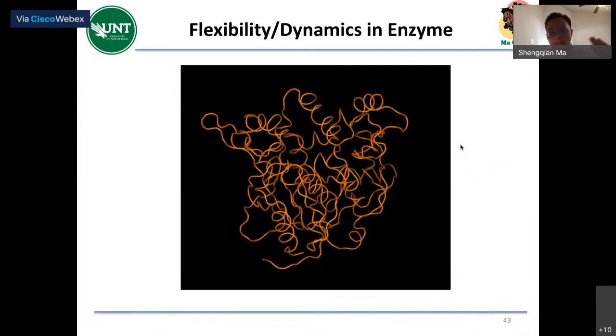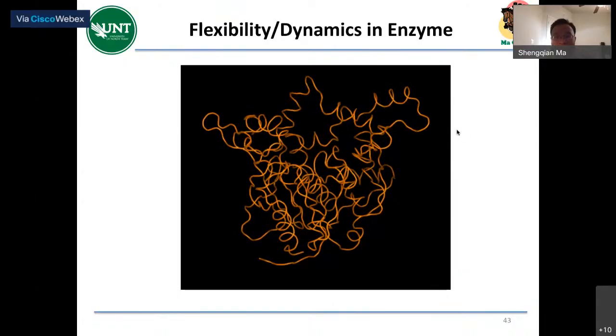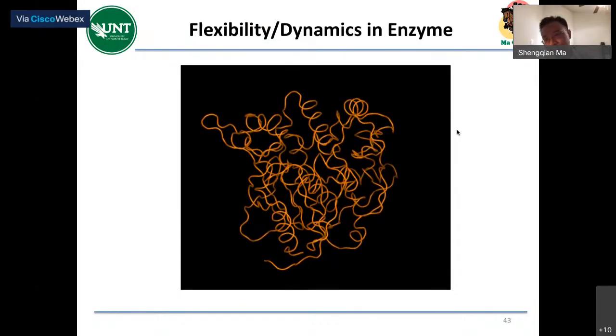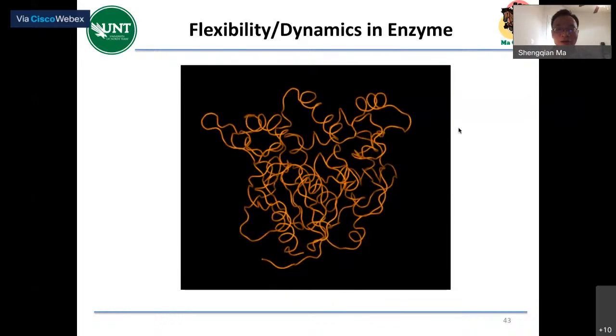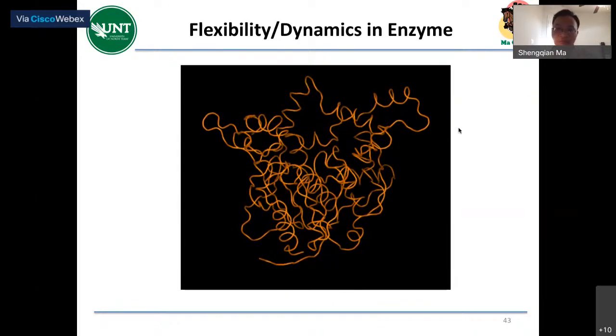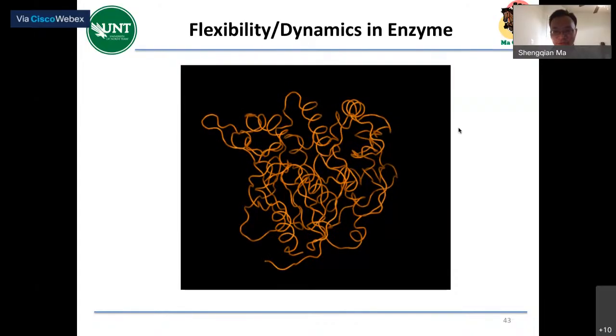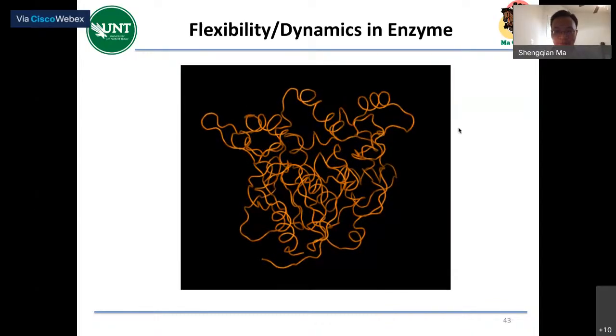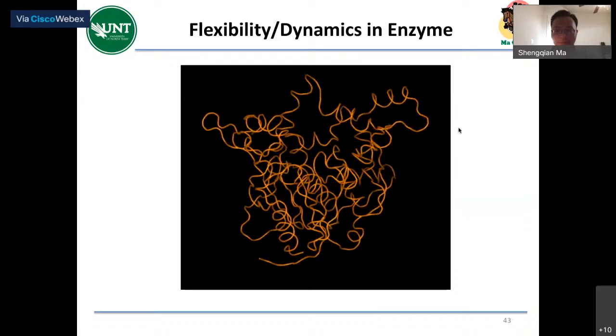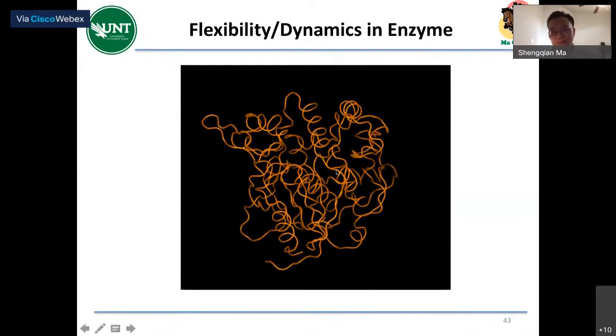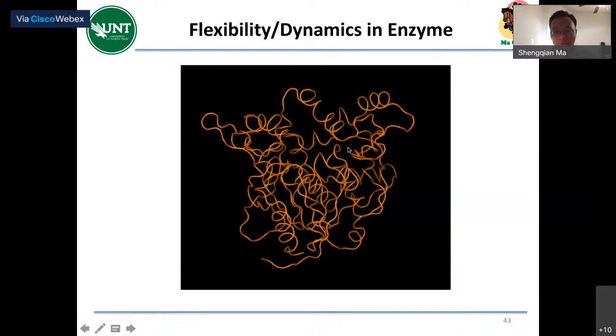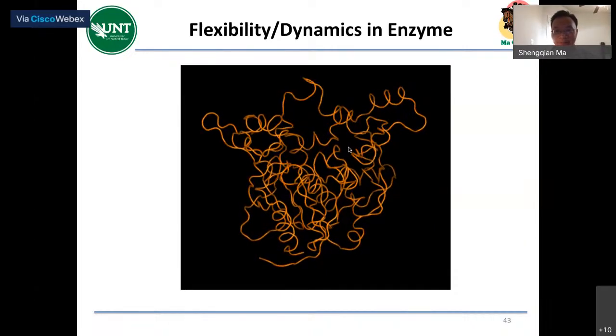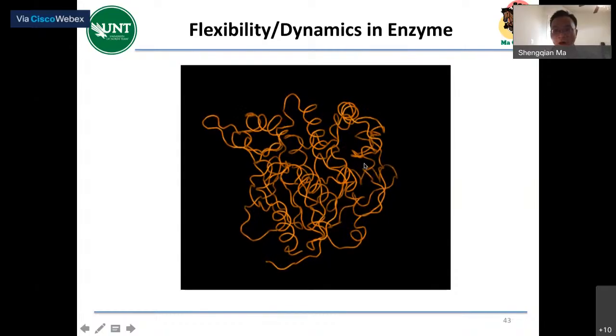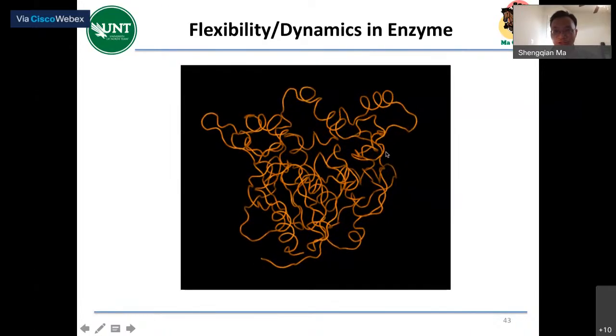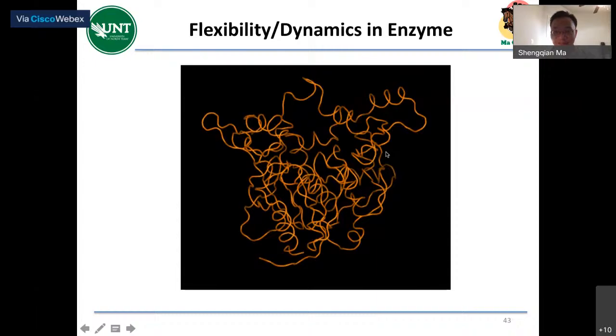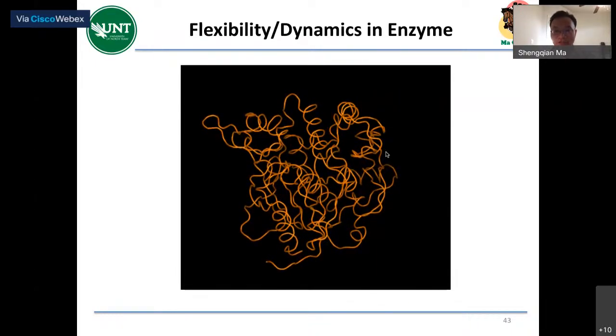So as I said, currently in industry for this additional CO2, they use high temperature, high pressure. As I said, one of our targets is to use the MOF to develop the MOF-based enzyme mimic system, to mimic enzyme. Enzyme can do this kind of reaction at very mild conditions, ambient temperature, ambient pressure. One of the features for enzyme we know, they're polypeptides, right? It's essentially the polymer, and it's flexible and dynamic. Because of this flexibility, they can cooperate. Different active sites, they have the freedom to cooperate with each other. That can do the reaction at a very mild condition.